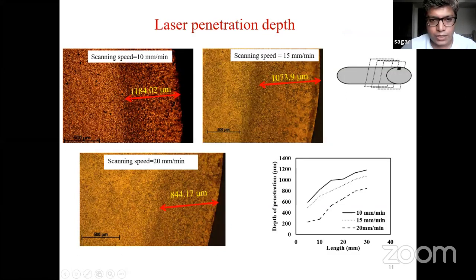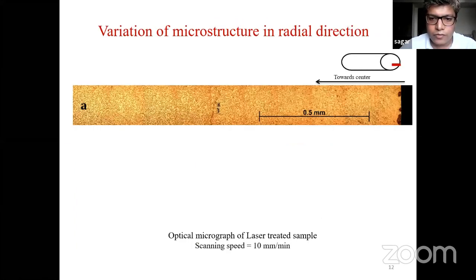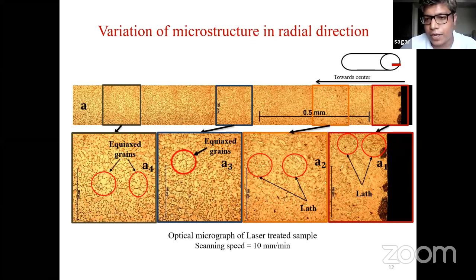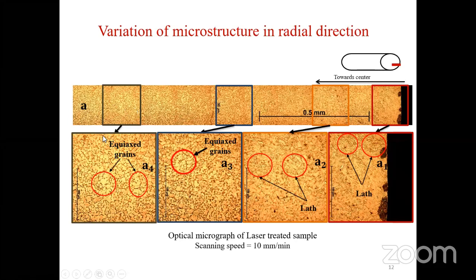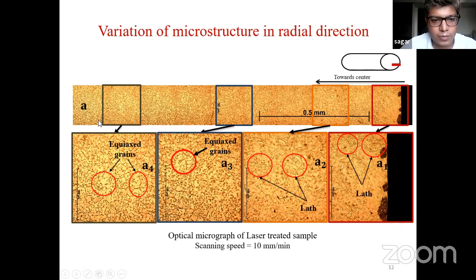So now what happens with this penetration? With this penetration, you could see the change in microstructure. From here, this is the end portion, and from here I took the laser scan. From surface to center, the structure has changed, and after a certain depth, you could get the equiaxed grains, which is nothing but the original structure of the material.